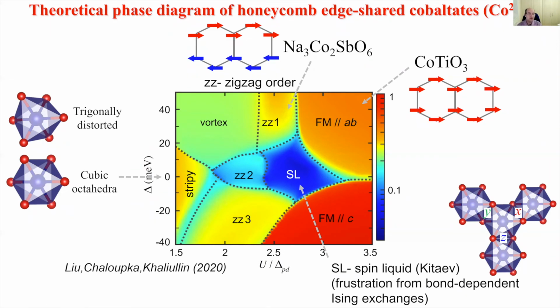I see. So really the key parameter to change is the trigonal distortion. If we get closer to the cubic limit, according to all the theoretical models proposed so far, that would be the place where the strongest competing interactions would occur. Okay. So we know that in cobalt titanate, there are bond-dependent interactions, but they're not dominant. We see evidence that they're there, but we need to go to the regime where they become dominant. Yeah.